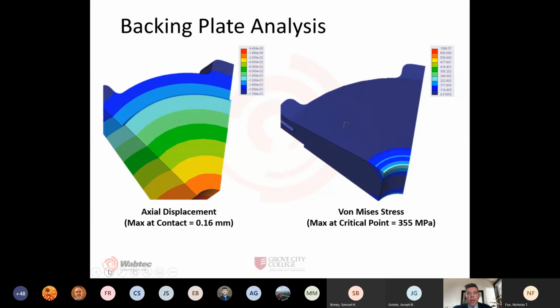The stress analysis of the backing plate originally resulted in a stress singularity at the washer and M42 bolt contact surface. And to gather more accurate results, a reversed loads analysis was created. And this analysis is seen in the figure to the right. The stress in this area of concern did not exceed 355 megapascals, which is significantly lower than the yield strength of the material used in the backing plate. Now I'm going to pass it off to Jake to talk about the clamps.